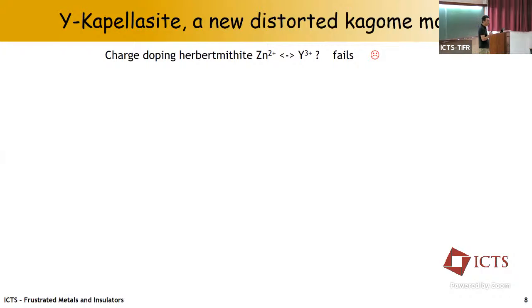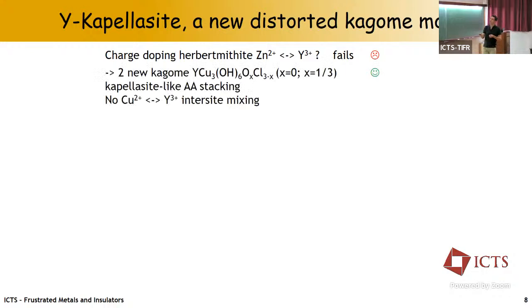Actually, so far, all the attempts failed, including this one. So somehow the system managed to incorporate this additional charge and stays insulating. But the positive outcome is that we ended up with two new structures. So the compound, basically, when you try to substitute zinc by yttrium, the structure changes.